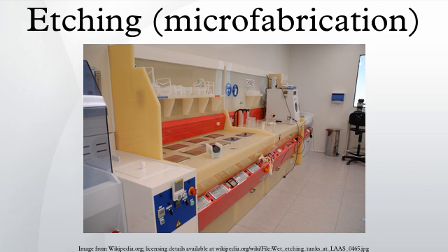This etch method is particularly effective just before back-end processing, where wafers are normally very much thinner after wafer back grinding, and very sensitive to thermal or mechanical stress. Etching a thin layer of even a few micrometers will remove microcracks produced during back grinding, resulting in the wafer having dramatically increased strength and flexibility without breaking.